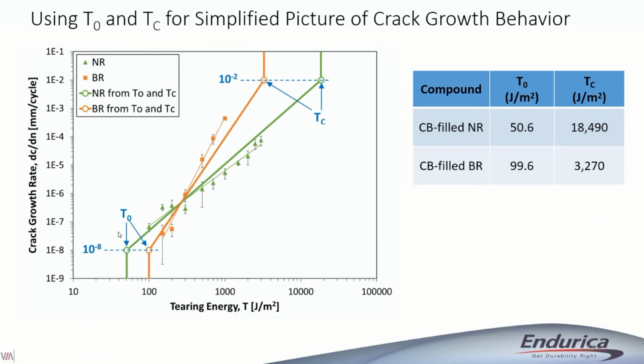What I want to say is using the intrinsic strength measurement, you can get a very approximate estimation of the fatigue crack growth rate curve. I like to call this Robertson's rule. Anybody who knew Chris Robertson while he was working with us, this is a correlation that he came up with. What he noticed was that if you draw a line at a rate of 10 to the minus 2 millimeter per cycle and 10 to the minus 8 millimeter per cycle, and intersect that with the crack growth rate curve,